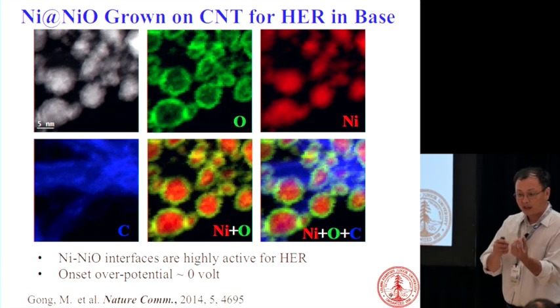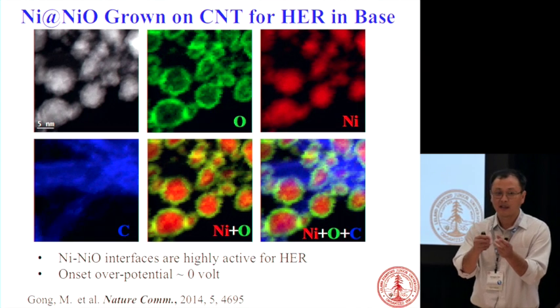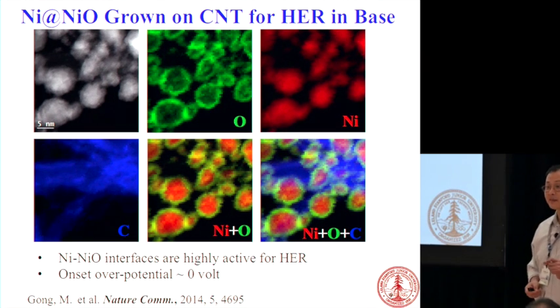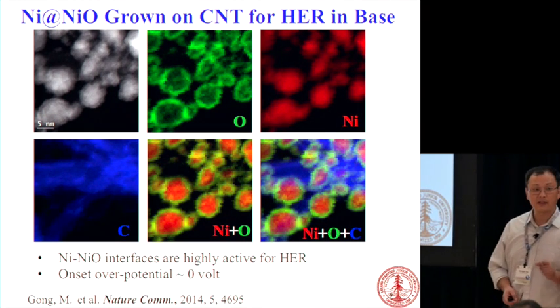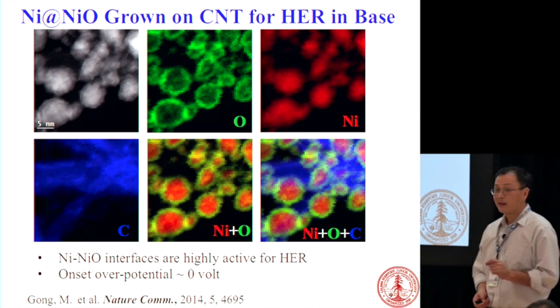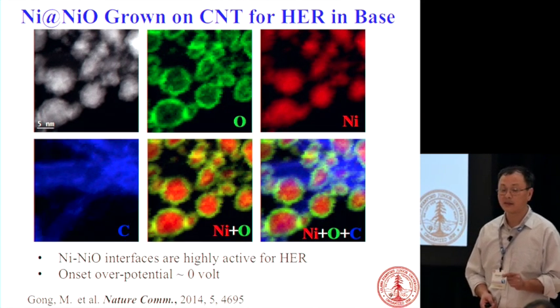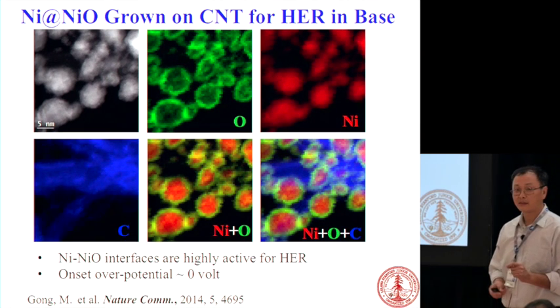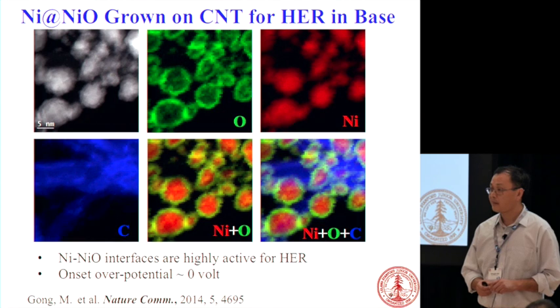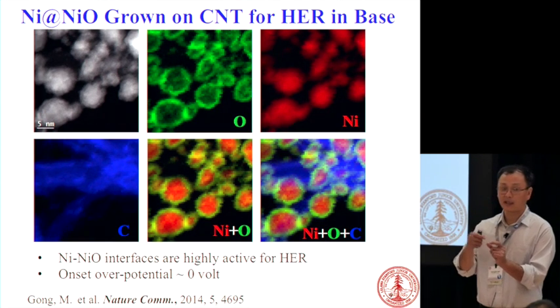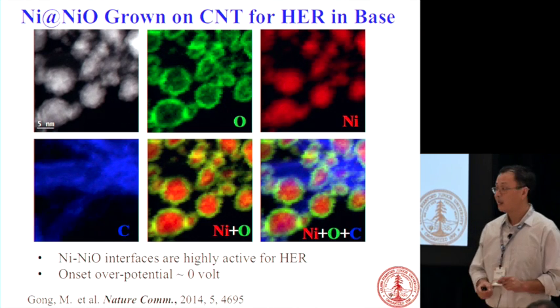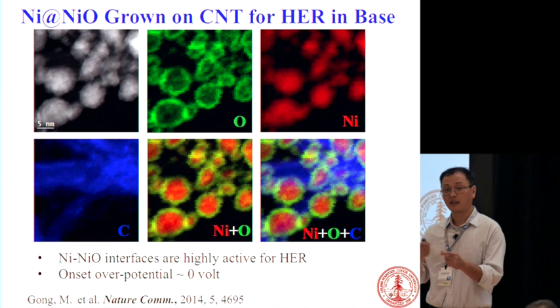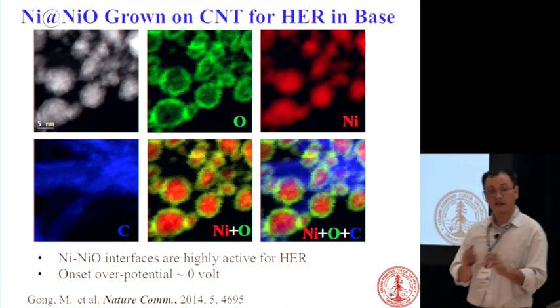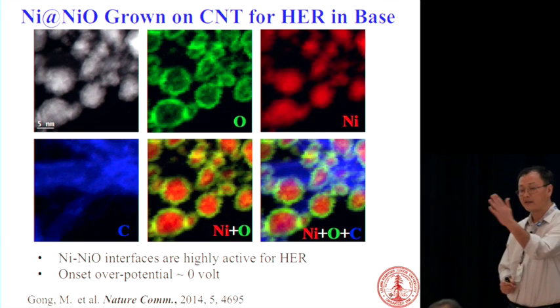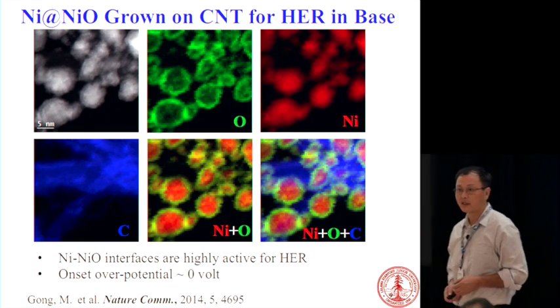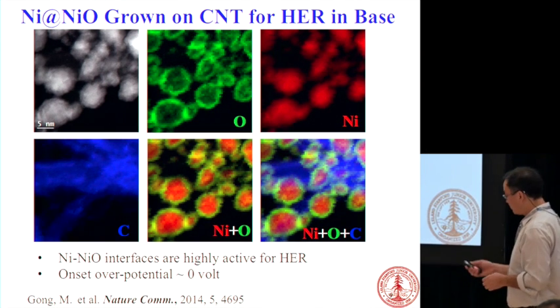Okay, so you make these, what we call heterostructures. You have nickel oxide attached to nickel metal. This material turns out to be very, very active for the hydrogen evolution reaction, and we have done theoretical calculations on that with collaborators. What we believe is happening is that when you have hydrogen evolution, the hydrogen atom can attach to the metallic nickel side, and then the OH groups, which are oxidizing species, attach to the nickel oxide phase. So that boundary of nickel oxide is what we believe is the really active site for producing hydrogen.